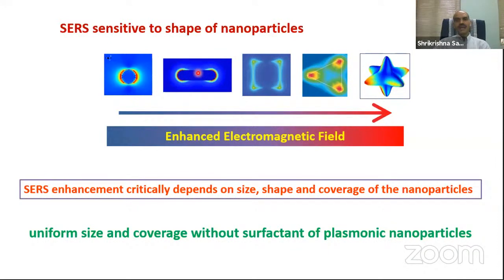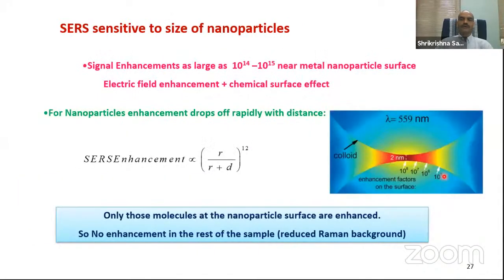So there is one thing we have to have. If I'm having, for example, spherical nanoparticles, they should be of the same size. They should be without surfactant. I want to put this point here, very important, because why surfactant? In the earlier slide, we have seen that whenever the probe molecule is away from that particular metal nanoparticle surface, the enhancement is decreased by 3 orders of magnitude. It means that if this nanoparticle surface is coated with some capping agent, usually you know that whenever you make a metal nanoparticle in chemical synthesis, the capping agent actually restricts the size of the nanoparticle. So what will happen?